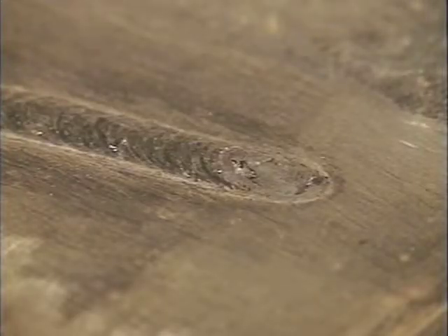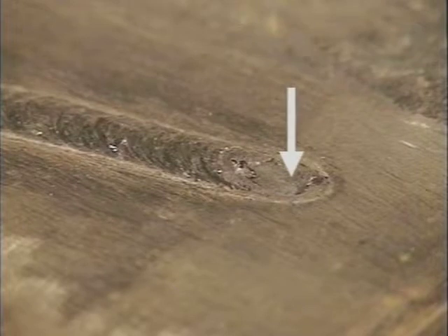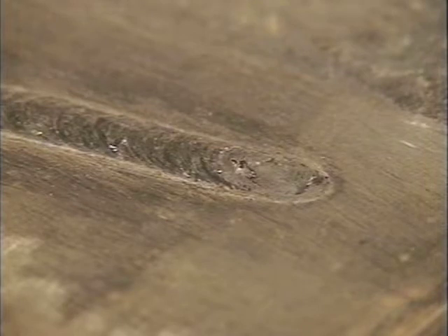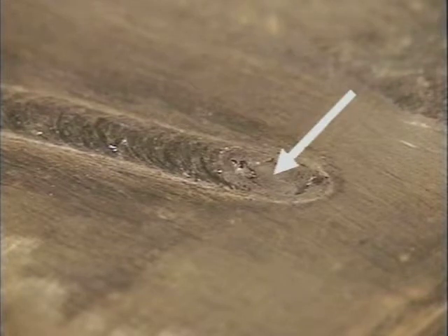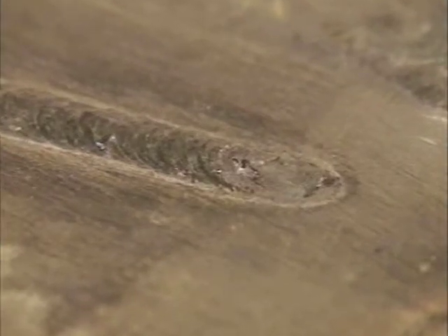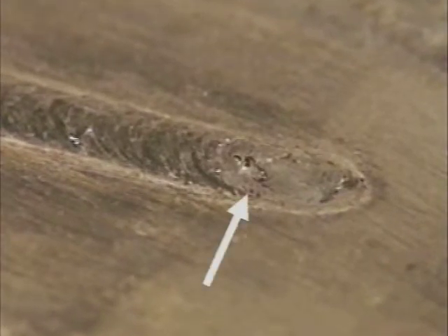When the arc crosses the gap, it melts the base metal, forming a molten puddle. That arc stream also carries the filler metal from the rod into the puddle. This is a E6010 weld bead that I pulled out of quickly. The leading edge of the puddle was actually below the surface of the metal. The strong arc force of E6010 and E6011 penetrates deep into the base metal and pushes the molten puddle back, building up weld bead. While you're welding, watch the sides, right where the weld buildup meets the surface of the base metal.